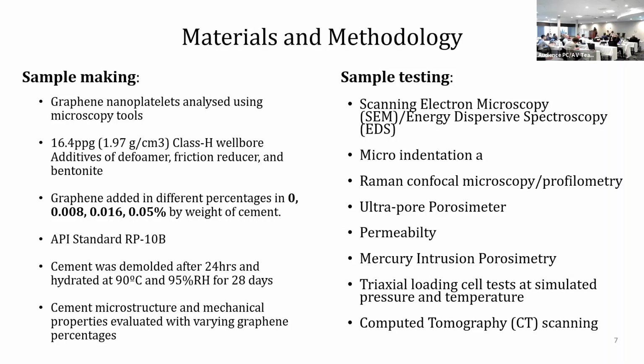We did not cure these cements at pressure. That's the only downside that I see in our approach. That was a limitation we had in our lab, and I think it's important to be open about that and report it. So the testing was thorough material characterization and mechanical characterization, because that was the important thing for these plugs to survive in the Gulf of Mexico, as some of these reservoirs go through repressurization.